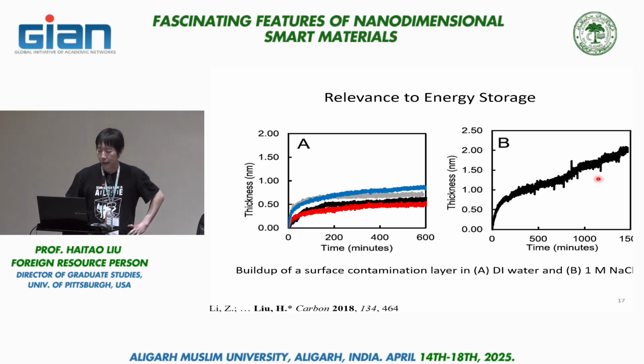We repeated the same kind of experiment using an electrolyte solution. This is 1 molar of sodium chloride. And you see the same kind of accumulation of contamination, we think, on the surface, except this is much faster, first of all. And second, it goes all the way to about 2 nanometers over a long time. And certainly there's additional sodium chloride. We didn't use any ultra pure sodium chloride. We just got sodium chloride from Sigma Aldrich, and that's what we used. And clearly there's more dirty stuff in this solution compared to nanopure water.